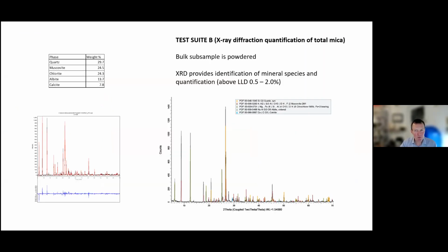Test suite B then for the mica pathway calls on X-ray diffraction. And this is an analytical technique that I have used for years. It allows the identification of mineral species and their quantification above what we term a lower limit of detection, which can be anything from 0.5 to 2% depending on the mineral species. So we won't see perhaps something at low concentration that is deleterious, but we will see things at higher concentration.